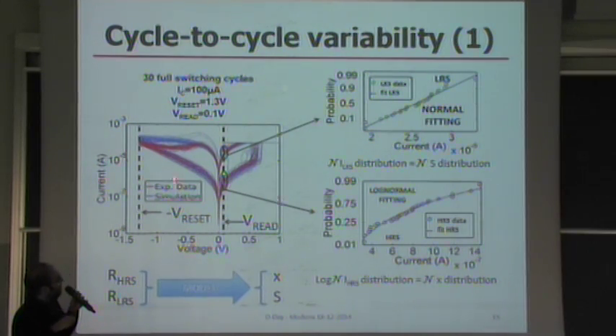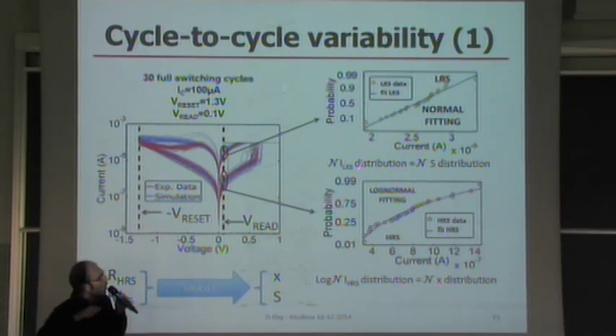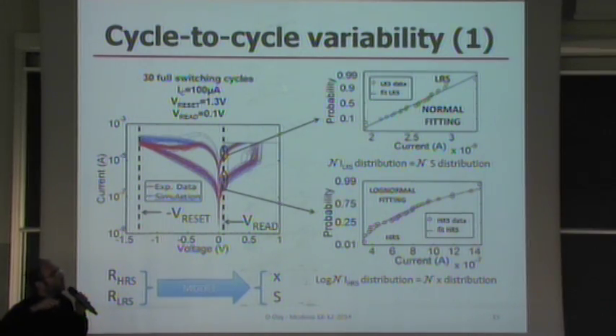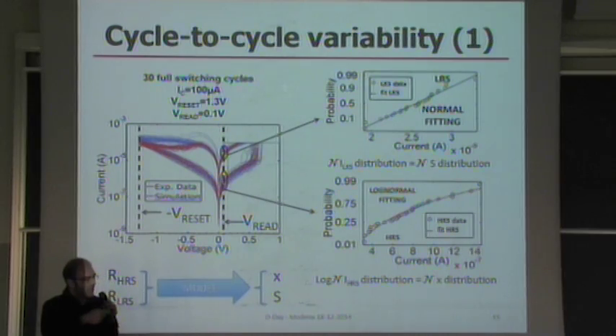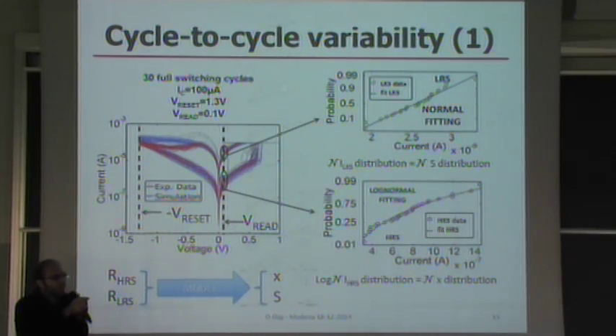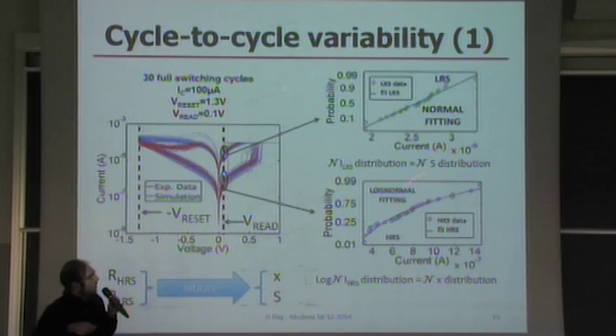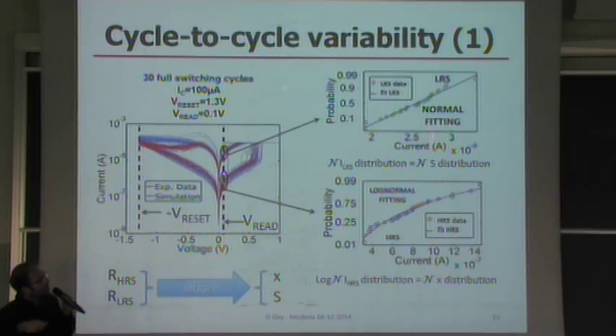These are the conditions, for example, of this particular example. And this is what we get when we look at the distributions. We have a distribution of values of the read current extrapolated from the IV curves. And as we can see, in LRS and in HRS, we have two different behavior. In LRS, we have a normal distribution of the current, and a normal distribution of the current is related to a normal distribution of the effective cross-section. This means that since the set process which drives the device in LRS is stochastic, each time we are going to form a filament which is slightly different in terms of effective cross-section. So that's why we have a normal distribution of the cross-section, which reflects to the normal distribution of the current.